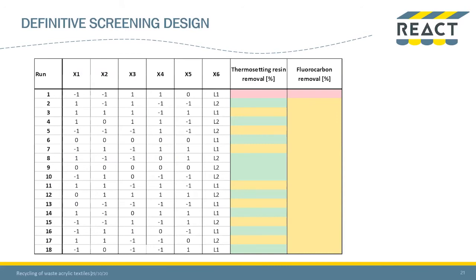So as an example of this design of experiment methodology, a one-step process was evaluated for which 6 parameters were tested. And this one-step chemical process resulted in complete removal of the thermosetting resin for some of the runs and partial removal of the fluorocarbons for almost all experiments. And how do we define those removal rates? This removal efficiency was determined using what I explained before, this change in peak height of the characteristic peaks in the infrared spectra of our samples.